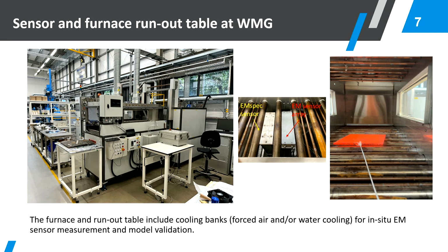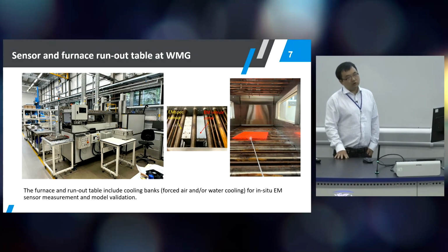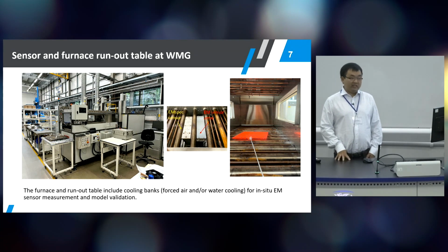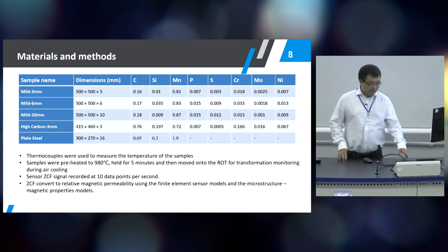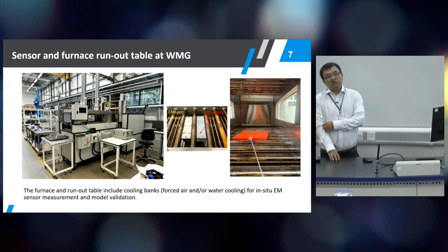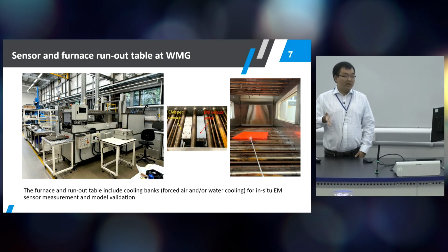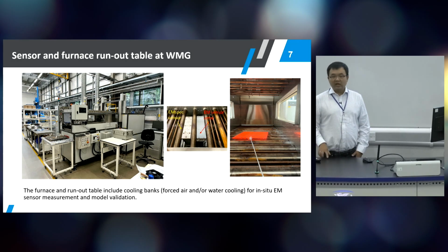What we are trying to do is heat the sample up to a certain temperature. We bring that sample out, and we stop it where the sensor is. To make sure the roller is still functioning, we sometimes move the sample forward and backwards, but the plate is still on top of the sensor, so that we can record how the sensor signal looks when a steel sample is cooled. Of course, in an industrial application we can't do that, because the steel strip is running continuously past the sensor. So you are having a snapshot of a temperature or a position, but if you have multiple sensor heads, they can then record the transformation behavior.